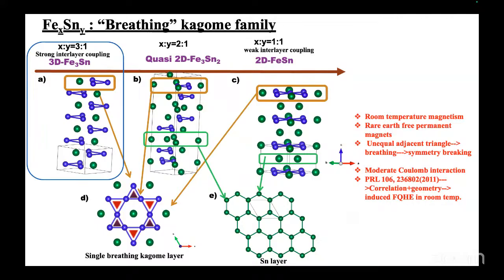So they have one Kagome layer over another, which is laterally displaced. So each layer is a Kagome layer? Yes, each layer is a Kagome layer. So there is a strong interlayer coupling of the Kagome, so it is more towards three-dimensional physics. And in the two-dimensional, the Kagome layer is separated by the thin hexagonal layer. So we get an isolated two-dimensional system, closer to the ideal Kagome system, which is isolated from the next one by this honeycomb structure.